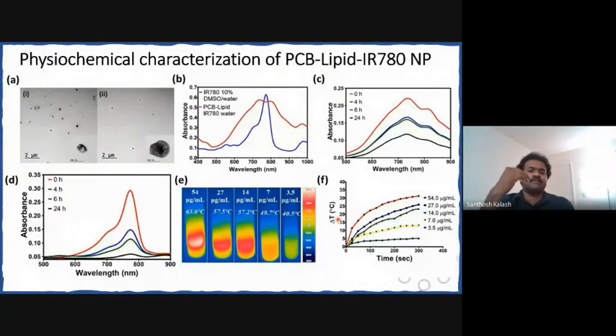Starting with the first data that we obtained, which is the characterization of this nanoparticle. We checked the size of the nanoparticles in a transmission electron microscope, and we also checked the hydrodynamic size in a dynamic light scattering instrument called a Zetasizer. Based on the TEM image that we saw, the nanoparticle, the polymer with the lipid alone, has a size of around 208 nanometers.